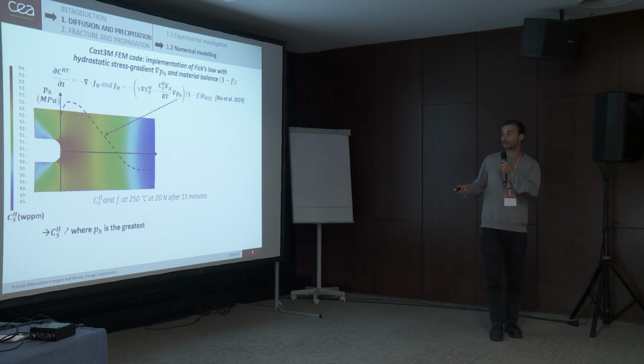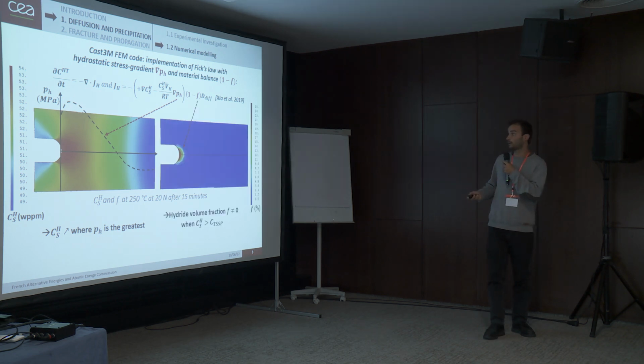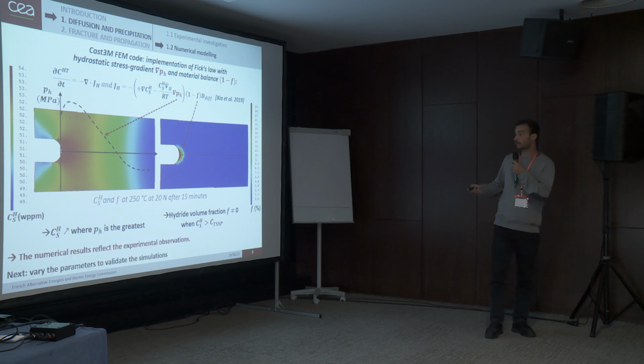So as you can see, this concentration increases where the hydrostatic stress is the greatest. And if we look at the hydride volumic fraction, you can see that it's different from 0 where the hydrogen in solid solution is bigger than the limit of solubility. So our numerical model results reflect the experimental observations, and now we are going to vary the parameters to validate